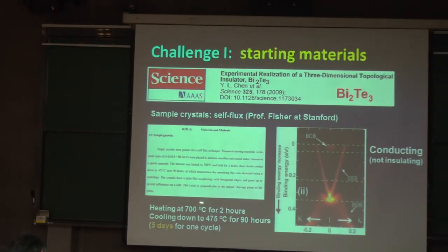So look at the procedure to prepare a single crystal. Of course, they take the high purity bismuth raw material and high purity tellurium, and they mix them together in the composition 2 to 3, and put them in a quartz tube, a very good quartz tube. Heat at 700 degrees for 2 hours. They cool down the temperature from 700 degrees to 475 degrees